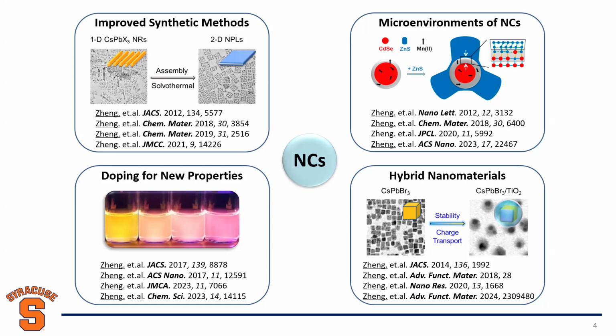After that, we move to the properties. How can we engineer the nanoparticles to have better performance? Right? So we have two strategies. One is to engineer the interior of the particles by introducing dopants, by changing the chemical composition. By introducing dopants, we can tune the optical properties and the magnetic properties. Another strategy is the opposite. We can do surface modification. We can engineer the material from outside. We do surface encapsulation and can make a hybrid nanocomposite.